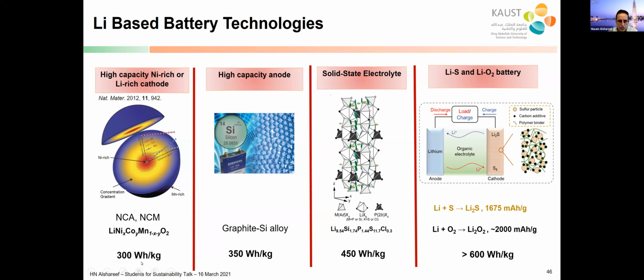And this can increase potentially the energy density of the battery to 300 watt-hour per kilogram. Another one is to introduce silicon, and I'll show you in a minute why. But in principle, the way this is going to work is likely not by using silicon entirely, but adding a few percent of silicon into graphite. You can get 350 watt-hour per kilogram.